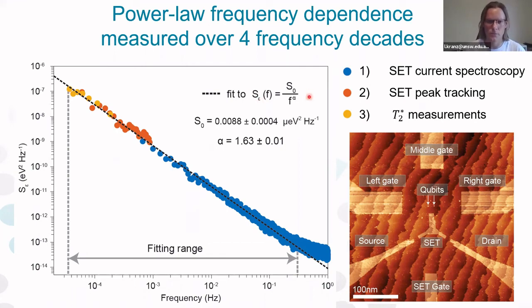Using this collective noise spectrum, we can fit the data, and we obtain a power law frequency spectrum described by this equation. Basically, you need 2 parameters to describe a power law frequency spectrum: S0 and alpha. S0 gives you the overall vertical offset of this line here, and alpha gives you the slope. Because we've taken data over 4 frequency decades, we were able to determine these parameters with high accuracy.